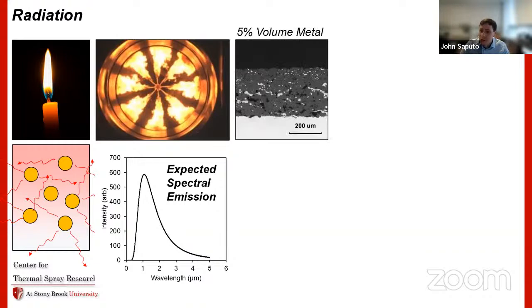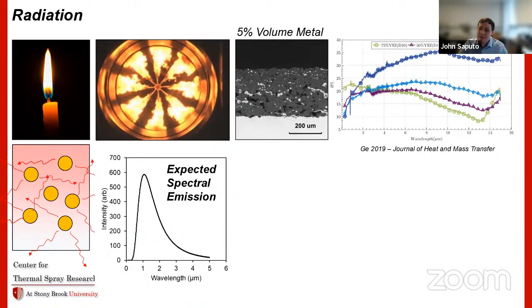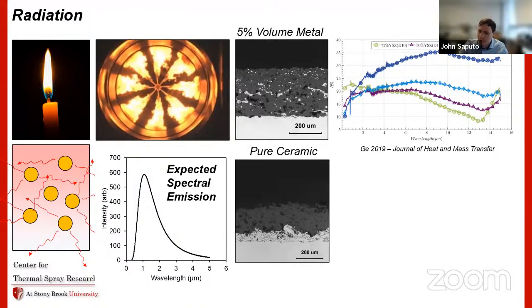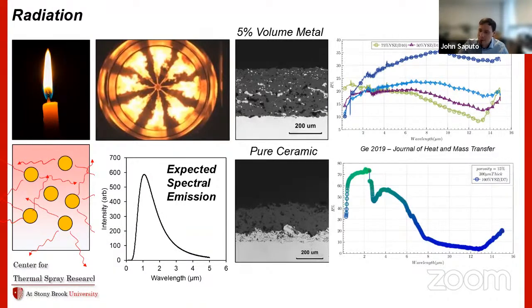If you look at the coatings, they have this 5% added metal volume fraction. If you look at the expected optical properties of these, you can see that the reflectivity, which is a decent metric, analog to the absorption of radiation in these systems, is about 20%. A traditional thermal barrier coating, like a pure ceramic coating, is about 70 to 80% reflective over that spectral range, which is interesting. So by adding that metal, we're toughening it, which is great. And we're not changing the thermal conductivity, but the propensity for radiative transfer is going up by a factor of about 3 just by adding that metal into the system. So our thought was, maybe that's bad. Maybe that's what we should be trying to take down in these systems.